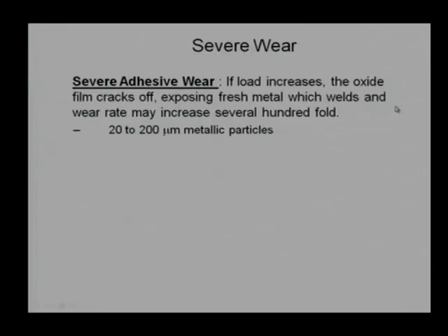That is why you say that there will be cold junction formation and wear rate will increase by several hundred folds. Reason being, oxide layer is lost, lubricant layer is lost, coefficient of friction is going to increase, wear rate is going to increase, and the particles which will come out from this mechanism will turn out to be in the size range of 20 to 200 micron.